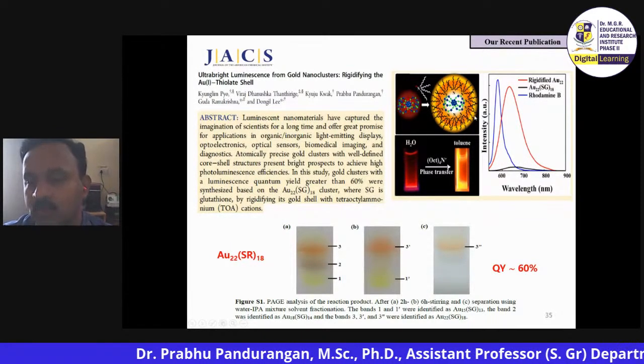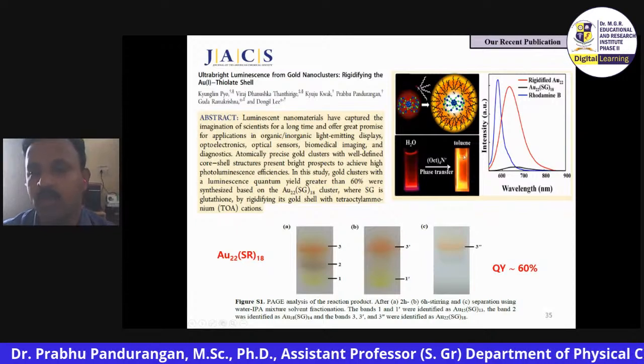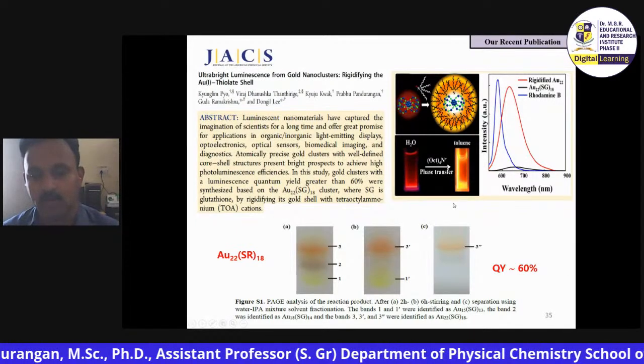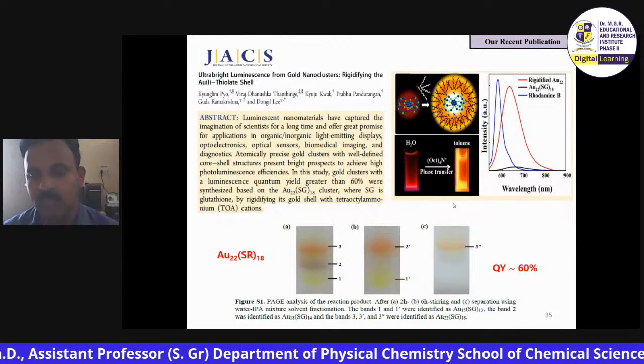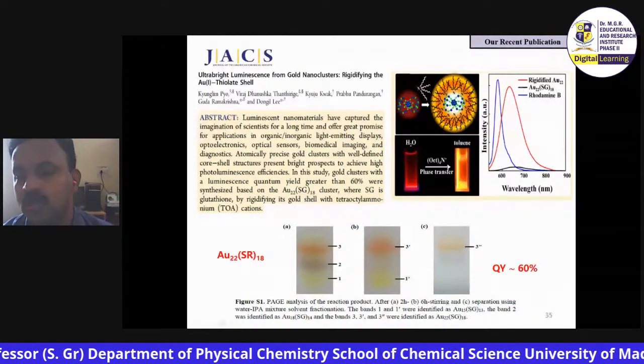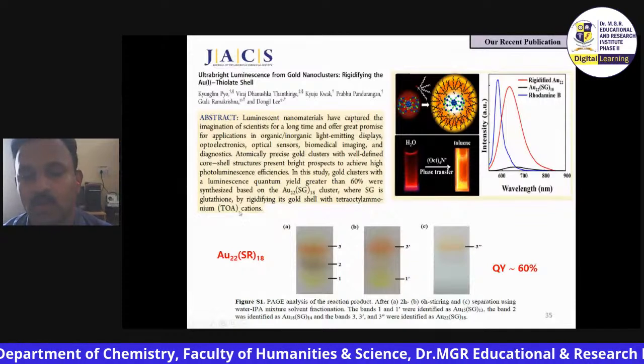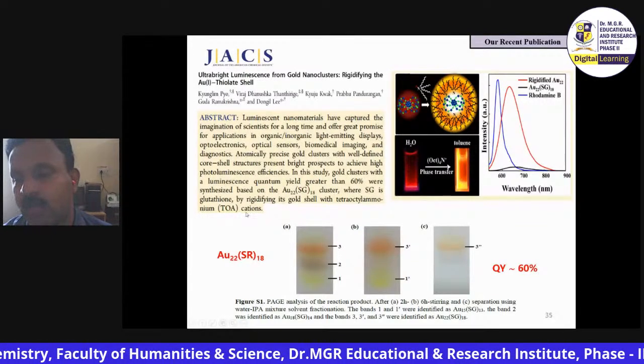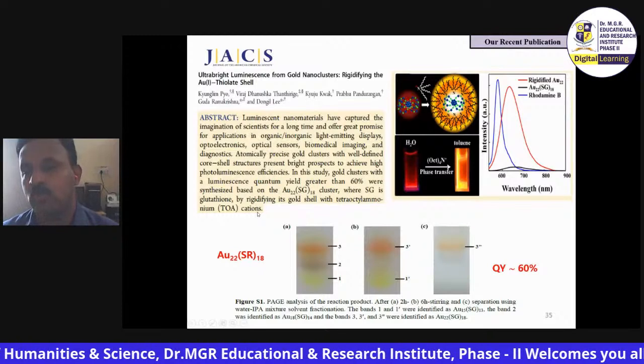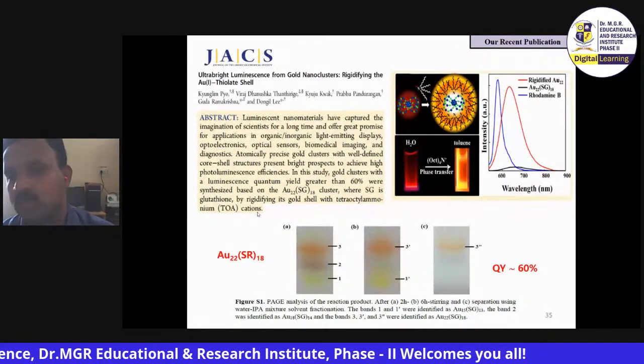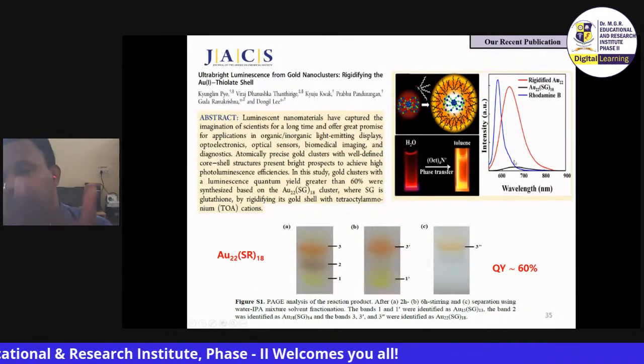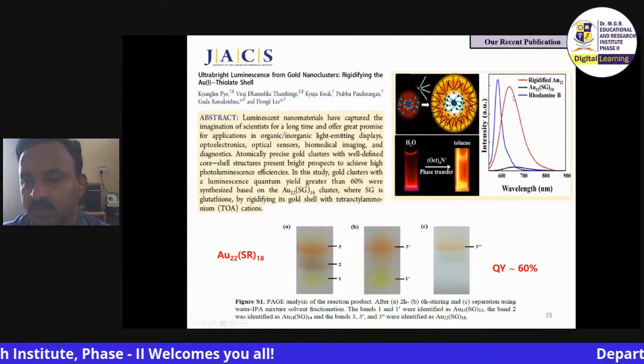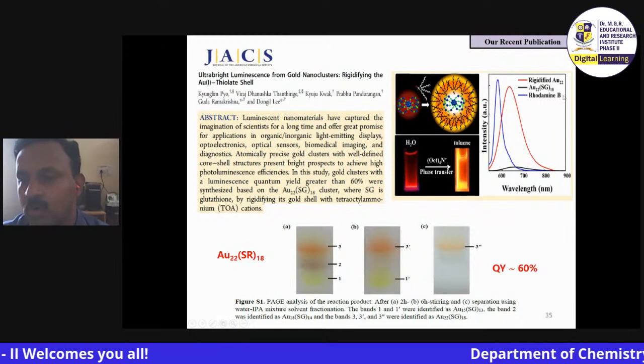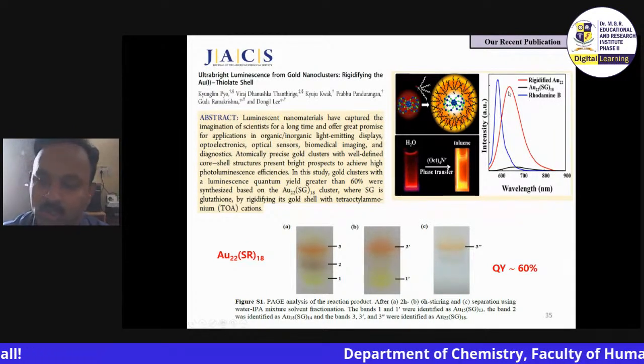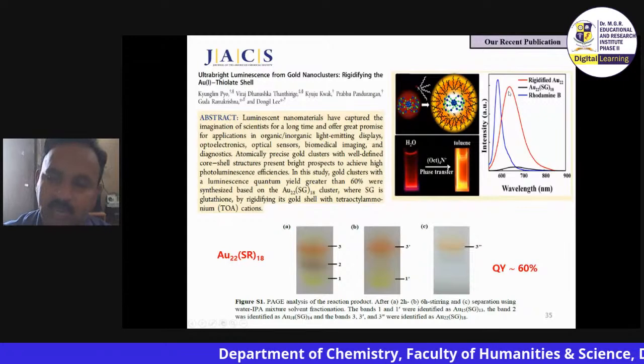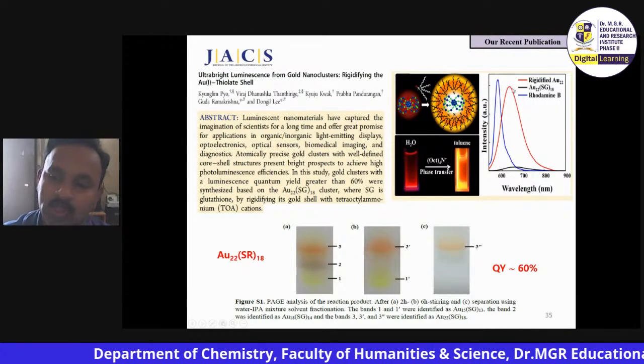Here, they used a phase transfer catalyst, because in photochemistry and photoluminescence, a rigid nature will increase the quantum yield. So we used TOA, the tetraoctyl ammonium cation, to shift gold 22 from aqueous to organic medium. Thereby the quantum yield was even more increased, to 60%. This is the conventional rhodamine dye quantum yield. Most people use this rhodamine dye as the standard, and it is performing better than the standard.